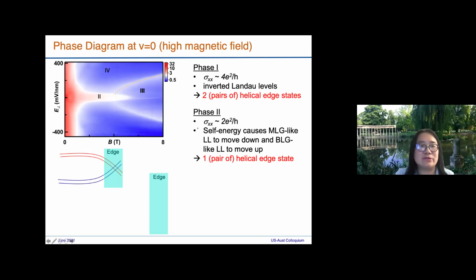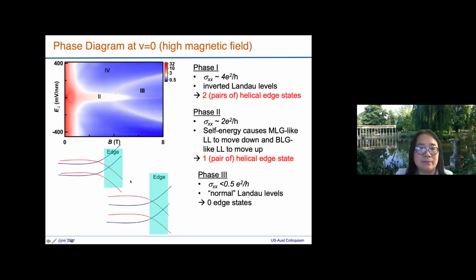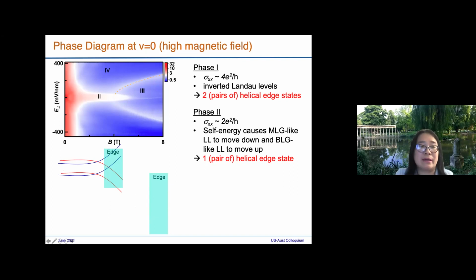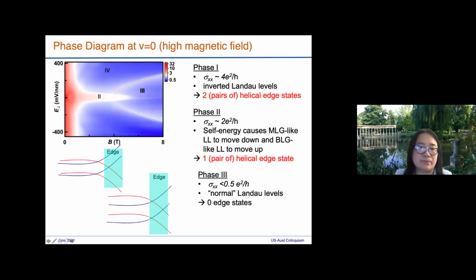Okay, so phase two is at a higher magnetic field. In this case, the calculation shows that the self energy will cause the blue band to move up and the red band to move down. At higher magnetic field there is also more Zeeman energy, therefore they are spin split. So now only 2 of the states are crossing here, and what we're measuring is 1 pair of edge states, and this gives us 2 times e squared over h.